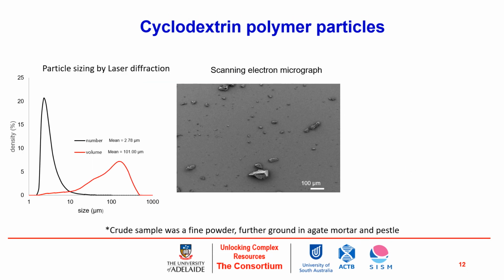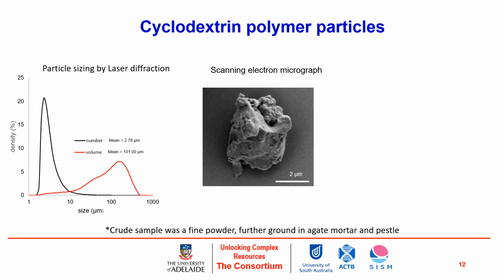Then I generated a series of polymers incrementally modifying this approach, eventually using an emulsion polymerization technique, which was able to reduce their particle size, shown through laser diffraction on the left-hand side of the slide and scanning electron microscopy in the center of the slide. You'll notice that they're quite craggy and sort of angular in many aspects. Although small, they did require further grinding to get to this size.